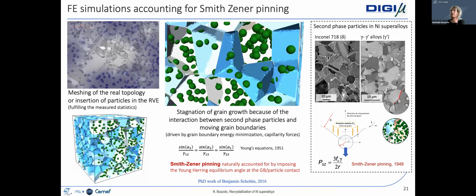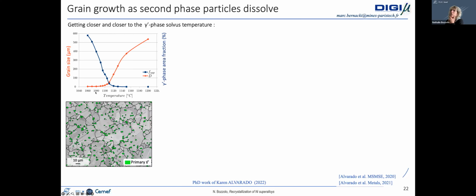So actually, this phenomenon is used in nickel-based superalloys to control the grain size. So here you see a microstructure of a gamma-gamma prime nickel-based superalloy, in which you see that the boundaries have stopped at the second phase particles. In such an alloy, if you go to higher and higher temperature, approaching the solvus temperature of the second phase, then you would see, of course, the volume fraction or area fraction of the second phase particles go down, and the grain size go up, because as the particles dissolve, the boundaries are released and the grain growth can start again.